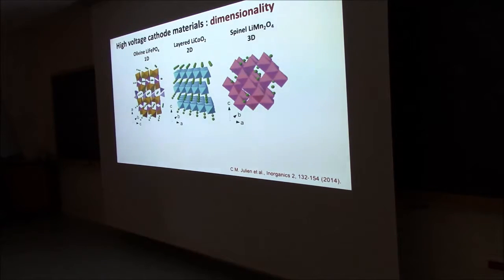So the materials that we are looking into, and which are, let's say, the standard materials in batteries, are these three. The one in the middle is the lithium cobalt oxide that has this layered structure, 2D structure. But there are two of them which are closely connected. On the left you can see lithium iron phosphate. There are the 1D chains in it where the lithium is moving. This is LFP, which is very stable, but it only gives you a 3-volt potential. And here on the right you have lithium manganese oxide, which is a spinel, and that has a 3D structure, so the lithium can move much more easily in all directions. So you can really think about 1D, 2D, and 3D, where you would expect, okay, that if you start playing with crystal orientation, you would expect the biggest effect in only a few of them.